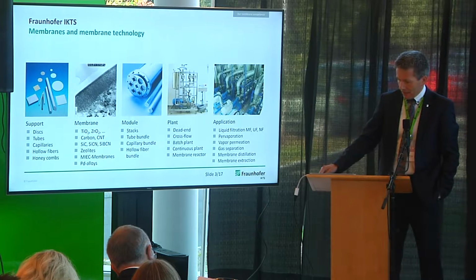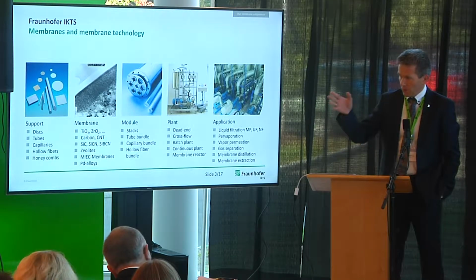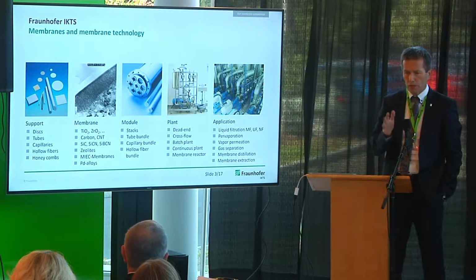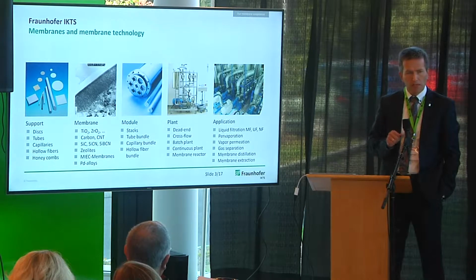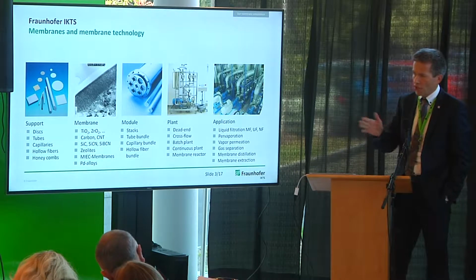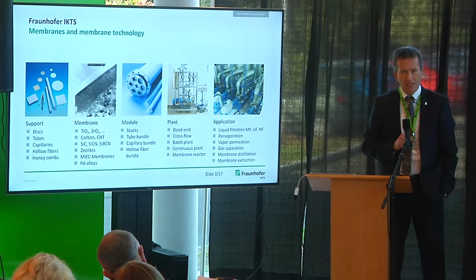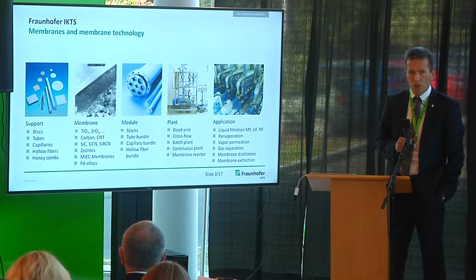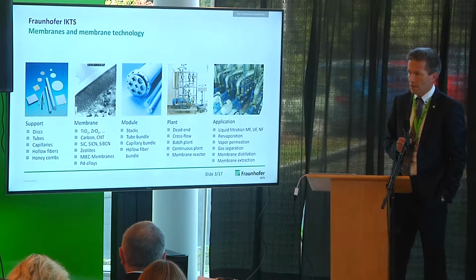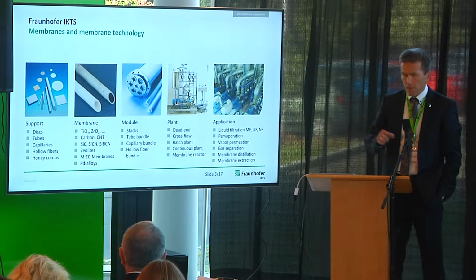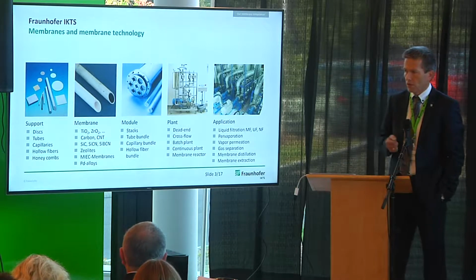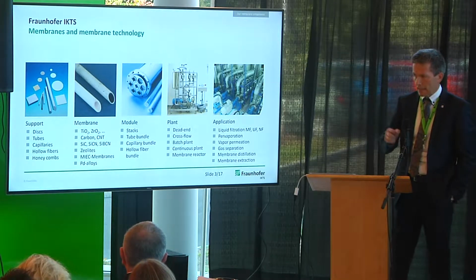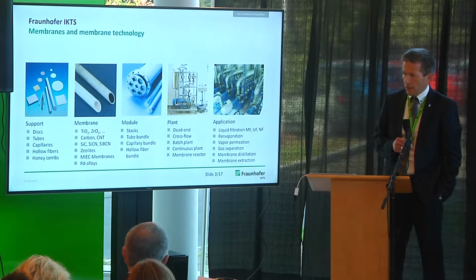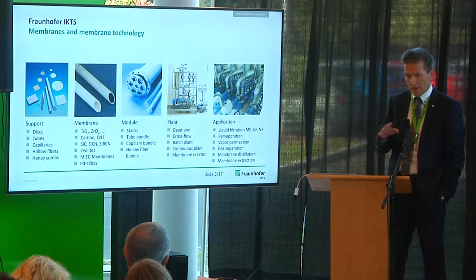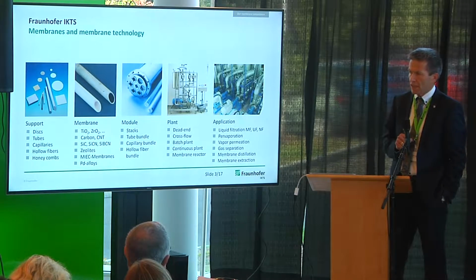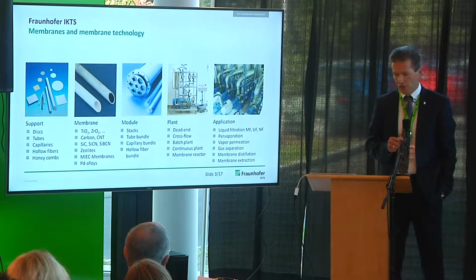Well, in the field of membrane development, we have different materials. We have in total about 50 people working on membrane development and membrane technology. One group is working on oxide membranes: titania, zirconia, alumina, as well as silica membranes. The second group is working on carbon materials: microporous carbon, carbon nanotubes, graphene. And in this group, we also perform development of non-oxide ceramics because it is a similar preparation technique. So we are working on silicon carbide, silicon carbon nitride.